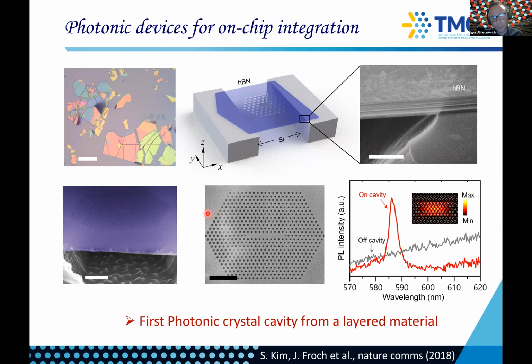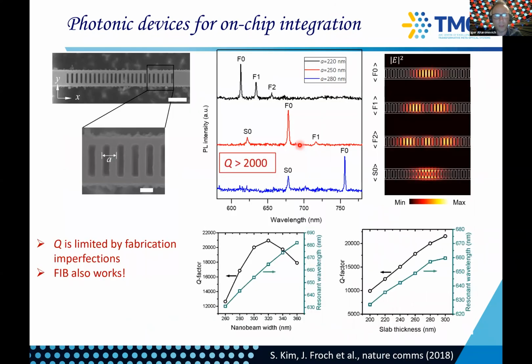So you can make these photonic crystals, and you can see there is a cavity mode, which is very low. For this, we need basically a slightly better design. So instead of having a 3D structure, we move to a 2D structure, and then we move to 1D. In a 1D photonic crystal, you can easily get quality factors of about 2000, right at the 600 nanometer range. This is the fundamental mode, and we can tune it by just tuning the repetition of these cavities.